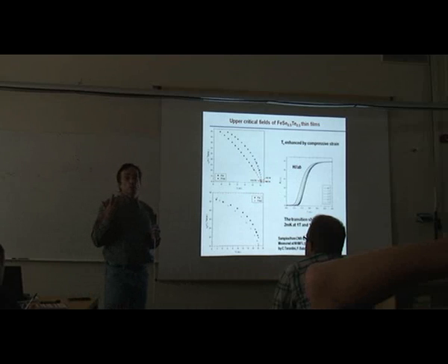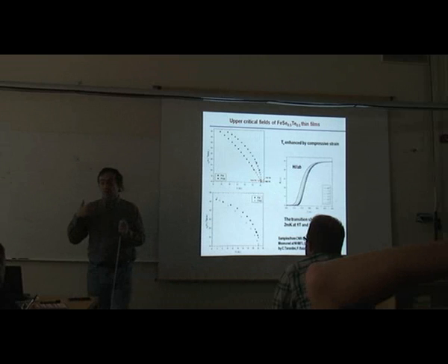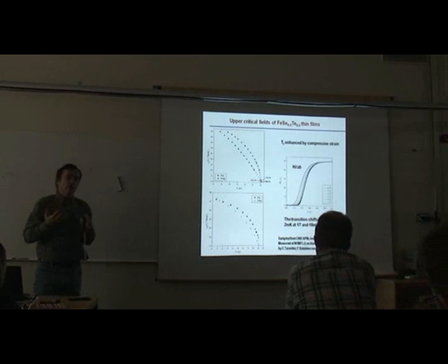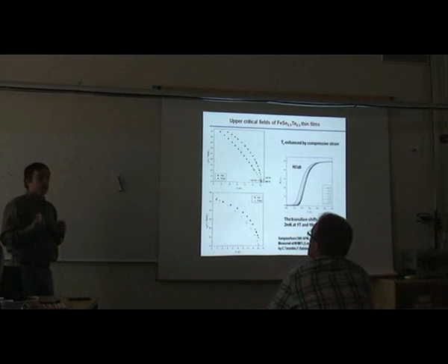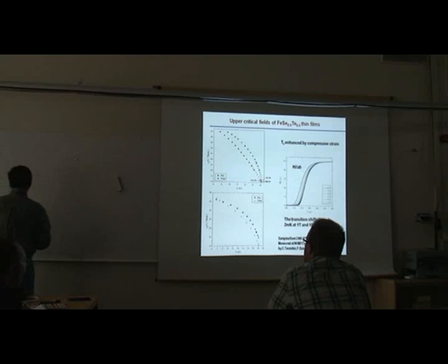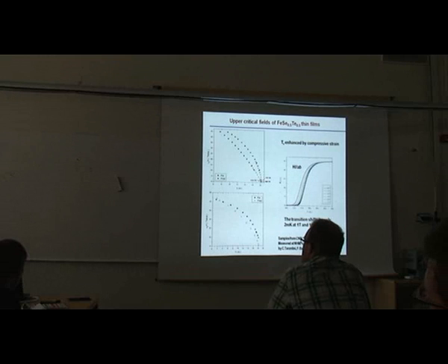So it is very suggestive that you have an FFLO state here. Because this kind of behavior tells us that paramagnetic effects are very strong, and if paramagnetic effects are very strong, then we have an FFLO state in which, let's say we have two bands. This is spin up and this is spin down. Now we pair this electron with this electron to form a Cooper pair, but because they have different momenta, the modulus of this momentum is not the same as this one. Then there is a delta P, P plus minus P minus. So the Cooper pair has non-zero momentum.